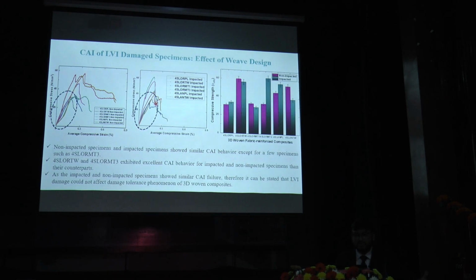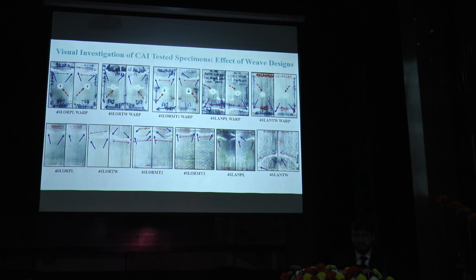I also did this CAI, compression after impact, and found quite an interesting story, which I can tell from the images here rather than the graph, that none of the load, even after the puncture, was damaged in the direction of where my impact happened. It means the through-thickness reinforcement did not let the compressive force come down to my punctured area.